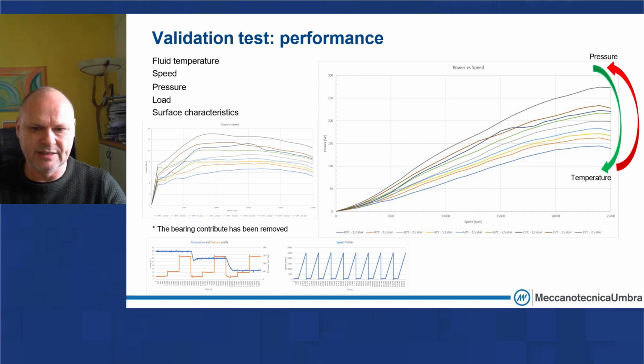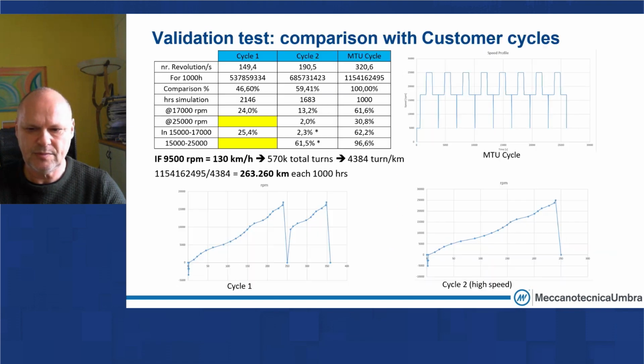I would like to come back to this slide to show you that the power consumption related to this sealing system changes depending on the pressure of the fluid and also on the temperature. So if the temperature increases, the power consumption is reduced. If the pressure increases, the power consumption is increased also. The typical range of the power consumption that we have in the tests we carried out is something between 120 watt to 250 watt. It's not small, but we will see how it's possible to reduce this amount of power consumption.